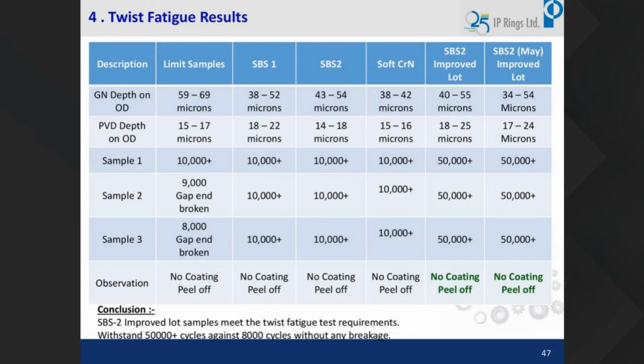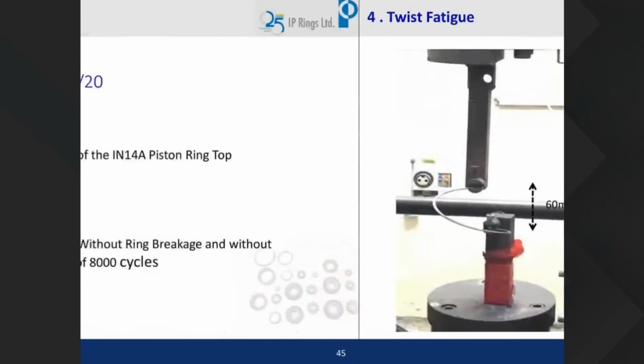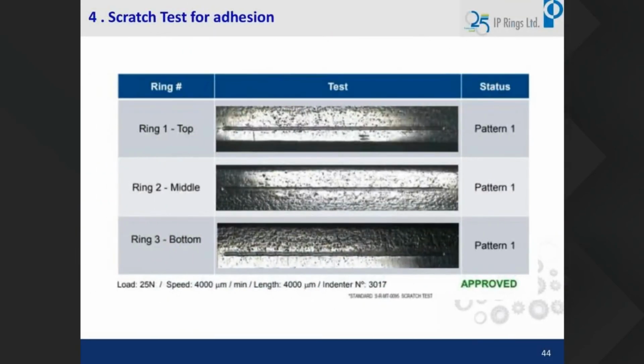This is a minimum cycle requirement, but we want to know what is happening up to 50,000. This is a customer requirement. We want to know whether it is failing when we extend the cycle. So for this, we subjected up to 50,000, and we couldn't find any peel off. The tested rings, after passing through twist fatigue, we send to the customer for scratch test evaluation, and it has passed in the scratch test evaluation also. These are some of the simple tests to see that the product is not failing during the service.